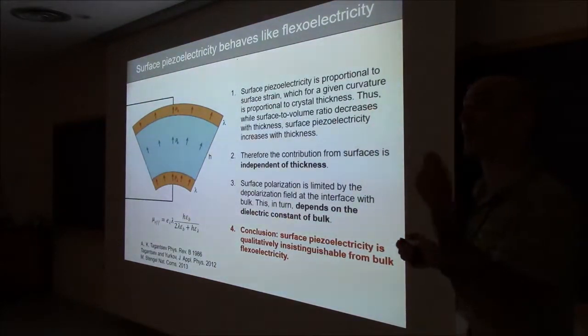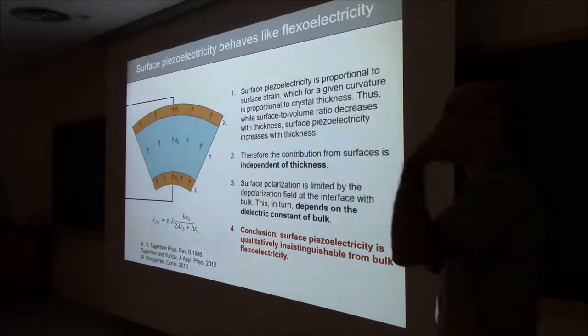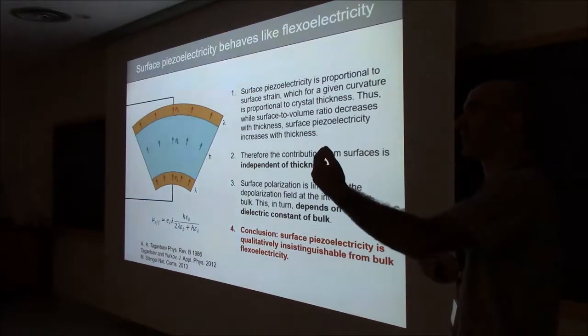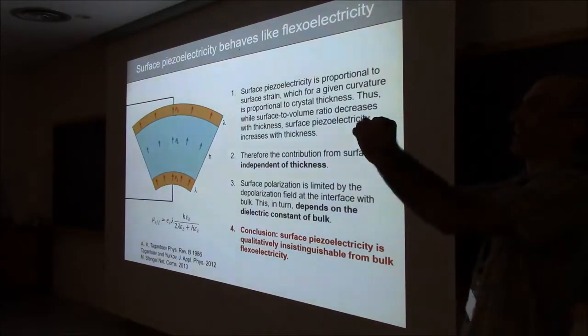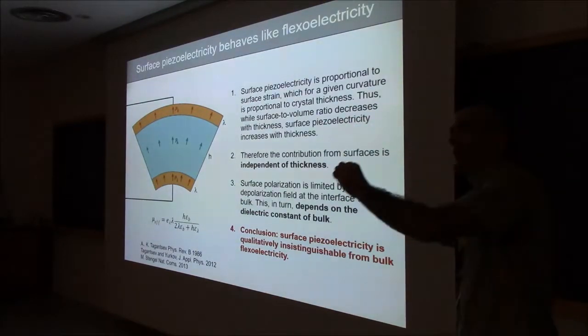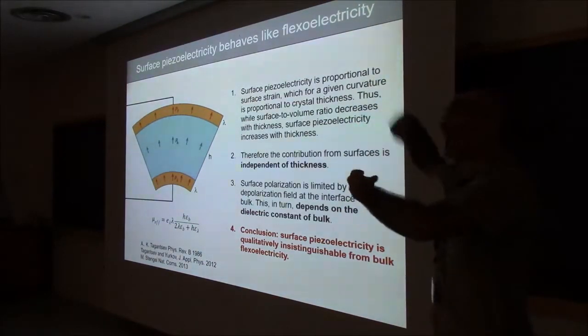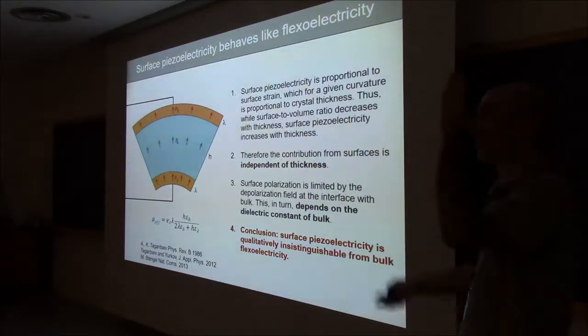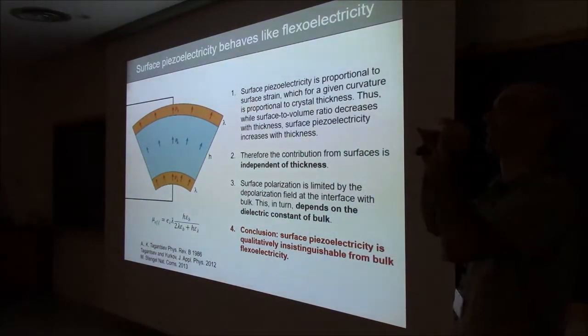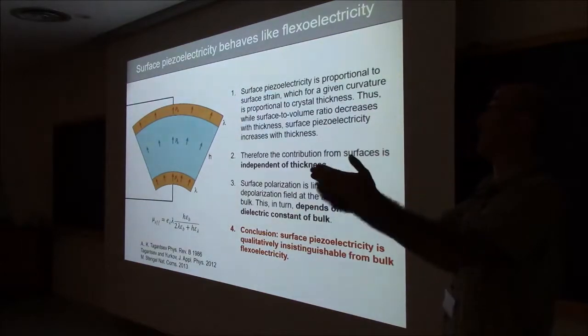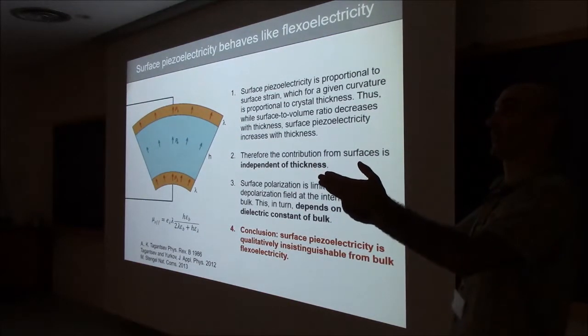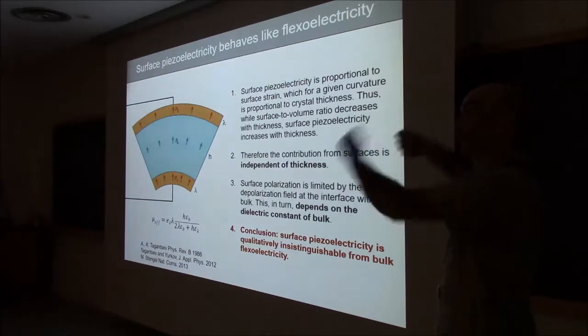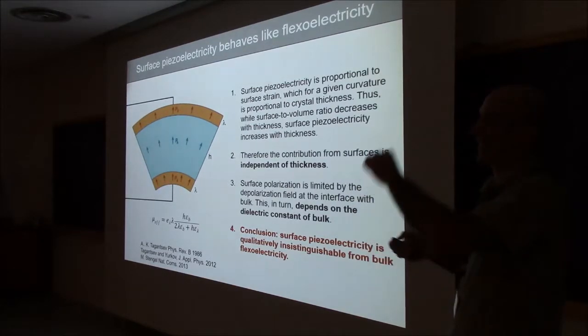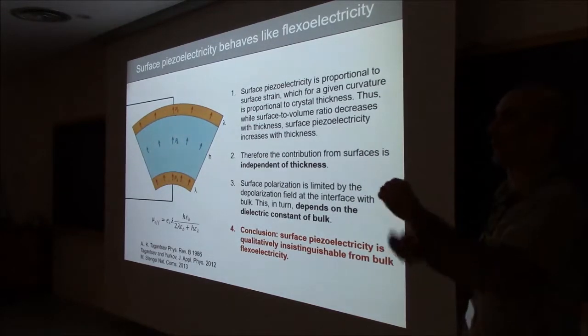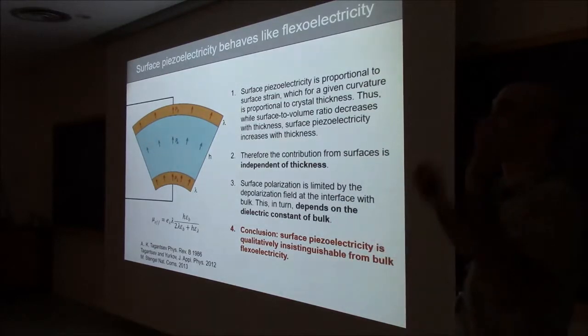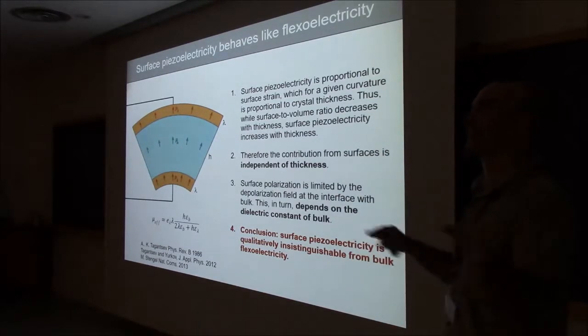So the surface piezoelectric contribution will increase proportionally to the thickness of the crystal. And even though the surface to volume ratio is decreasing linearly with thickness, the contribution from the surface is increasing linearly, which means that when you take the two effects into account, the surface piezoelectric contribution is independent of thickness. So the surface piezoelectricity is growing proportional to the thickness. The amount of surface compared to the volume is decreasing proportional to the thickness. One thing times the other means independence of thickness.